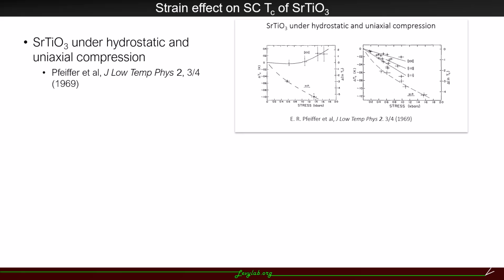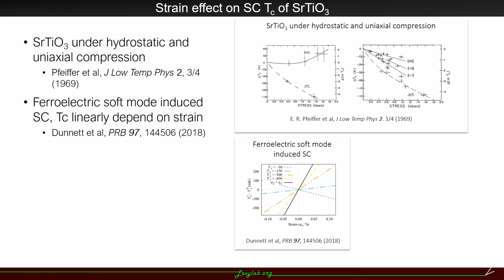There have been many studies on the strain effect on superconducting phase transition temperature Tc of bulk strontium titanate. Early experiments observed decreases in critical temperature under hydrostatic pressure, while seeing both increase and decrease for compression along the 100 axis. Theoretical calculations predicted a linear dependence on uniaxial and biaxial strain, meaning that the transition temperature decreases when the sample is compressed, and increases when it is stretched.